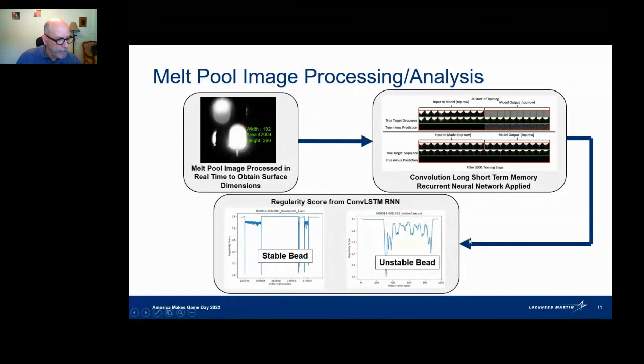By looking at a stable bead versus an unstable bead, if you pay attention only to the straight, steady line up here, these others are transient at start and stop. The stable bead gave a very uniform regularity. We purposely induced an unstable bead. And when we did so, you can see that this neural network would predict that instability. That instability was literally moving into the dripping zone. That's how we generated that instability.